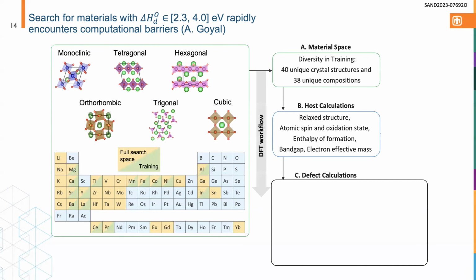Anuj is my collaborator at NREL who does the DFT on this. If we're looking for oxygen vacancies in this critical range, we rapidly encounter computational barriers. He's screened a wide range of material space, those green half triangles, but in reality, we want to look at basically anything that's also in yellow. It's a really hard problem because the DFT is not simple. You need magnetic sampling for these correlated materials. You need to do all sorts of difficult DFT calculations.